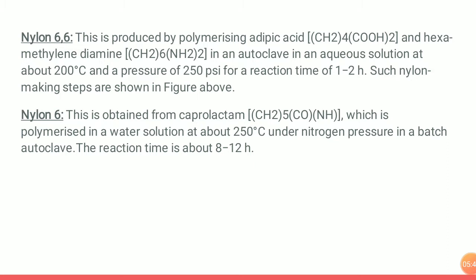Then the next type of nylon is nylon 6. It is generally made up of caprolactam, which is polymerized in water solution. The temperature is around 250 degrees Celsius, under nitrogen pressure, in a batch autoclave. The reaction time required is 8 to 12 hours.